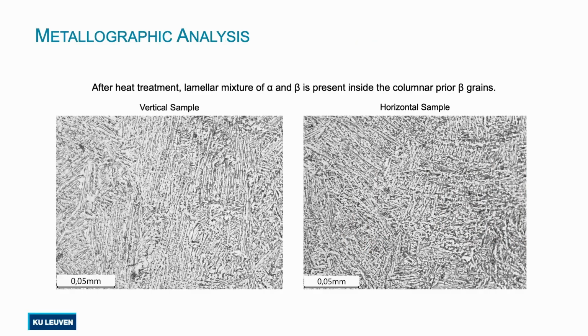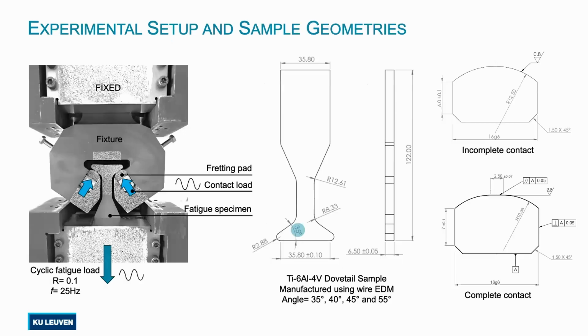From a microstructure point of view, we found a typical alpha-beta structure, which is very common for this kind of 3D printed material. Again, we did not see any abnormality related to microstructure that could jeopardize the results of the fretting fatigue test that we do. Here is the setup that we tried to develop.